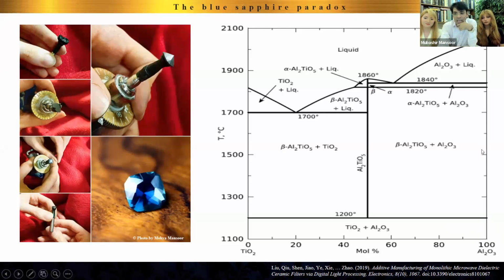But the problem is, anywhere I am on this map, I sit somewhere in here. That means I do not have just alumina or sapphire. I have both this aluminum titanate kind of compound along with sapphire. So that means I have two materials. Now, I want one material. I want it all to be sapphire. I want it all to get into the solid solution. But the problem is, any phase diagram that you open for the combination of titanium dioxide and aluminum oxide, that is sapphire, we always see these binary compounds, these two types of different material. So we do not see these becoming a solid solution. So this is a problem.